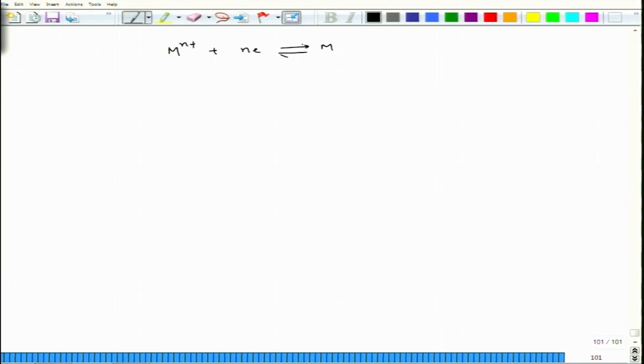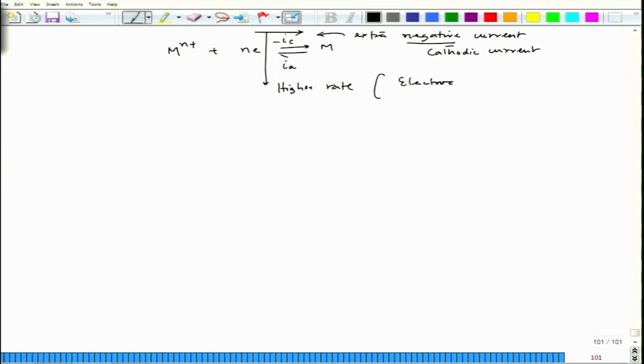So, if this equilibrium is disturbed, and how can we disturb? This is I c, this is I a with a negative sign. Let us say I supply little extra negative current. This negative means we are supplying little extra cathodic current, which is opposite to the anodic current. So, then this reaction would happen at higher rate. So, if it happens at a higher rate, that means this reduction process happens at a higher rate in order to maintain that reduction current density. It means that the electrode potential would switch to the negative side.